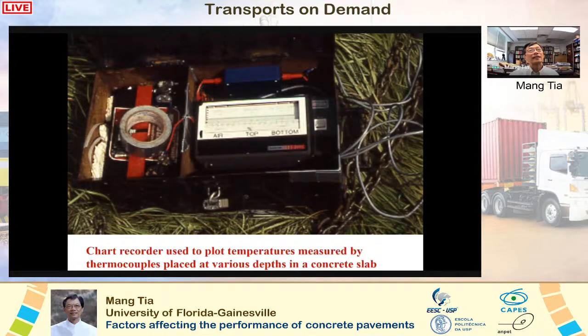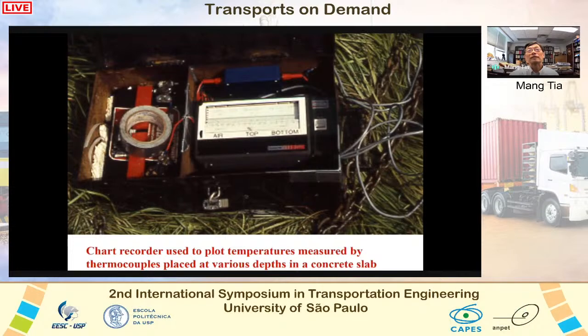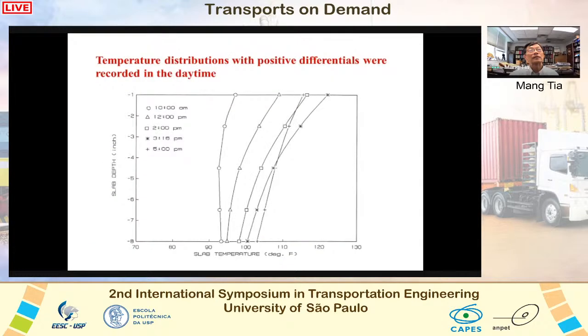In those days, a chart recorder was used to record and plot temperatures measured by thermocouples, which were placed at various depths in the concrete slabs. These are a few typical temperature distributions in a concrete slab at different times in the daytime. In the daytime, the temperature of the concrete was higher at the top than at the bottom, as you can see from these plots.